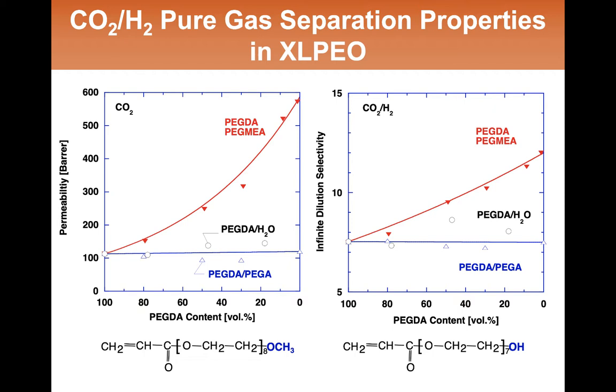And so this is showing first carbon dioxide transport. For the case where the Tg didn't change very much, that is, the molecular motion didn't change very much across this composition range, there's virtually no change in transport properties. And this is counter to the case that we saw with bare and sulfur cross-linked natural rubber. As the cross-link density there went up, permeability properties went down by close to 100-fold in some cases. Here, as the cross-link density changes, it goes higher and higher as you go right to left, virtually no change in transport properties. And again, this is showing that cross-linking really doesn't have much effect on transport properties if it doesn't change the rates of molecular motion.